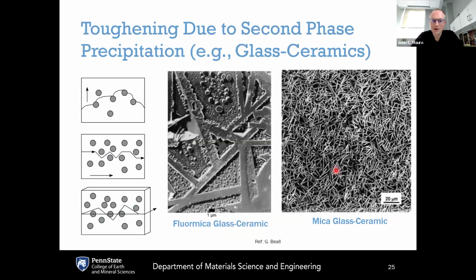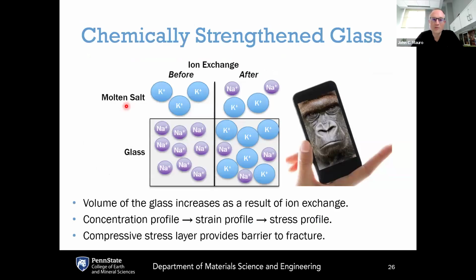Toughening due to glass ceramics is basically growing crystals in order to deflect cracks. So this is a very effective way to improve fracture toughness. This is what makes Corningware work, for example. And of course, we have ion exchange. Ion exchange gives you the highest level of compressive stress.